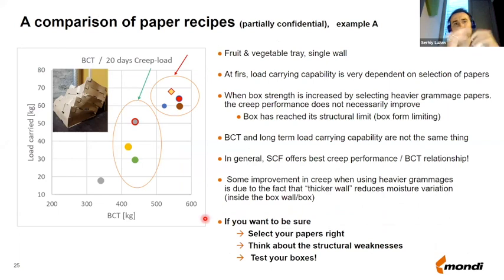Also very interesting that depending on how strong the boxes are, there are also different behavior in creep. So on this graph here, you see how the boxes with different BCT values, so how much load they can carry for 20 days. And you see that in the mid range of BCT values, for the same BCT, the boxes are showing quite large differences in terms of how much load they can hold over the time. So actually, you can reach similar BCT value with different raw material, but it does not mean that the boxes will behave the same way in the supply chain.